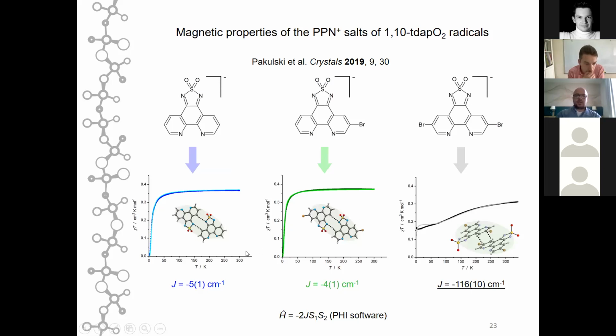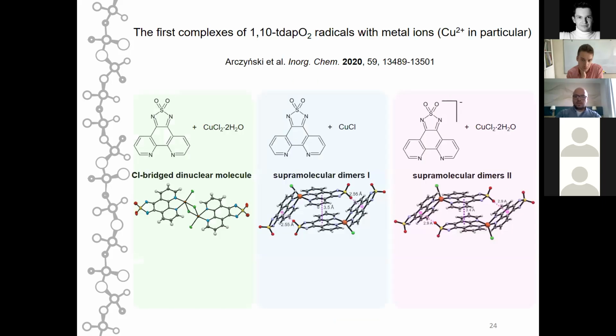So you can see that as long as the flat layers are maintained, the interactions are pretty weak. The hydrogen bonding interactions here lead only to very weak interactions. But if you go to the stacking interactions, we estimated it to be minus 116. It's lower than what we reported for the 4,7, but we believe the offset between the pi-pi stacks actually controls the magnetic interaction in this kind of crystal packing.